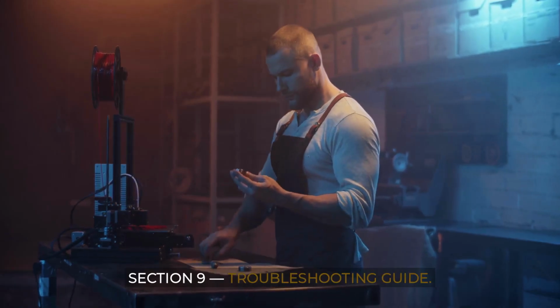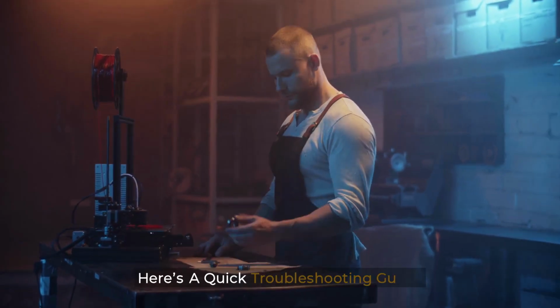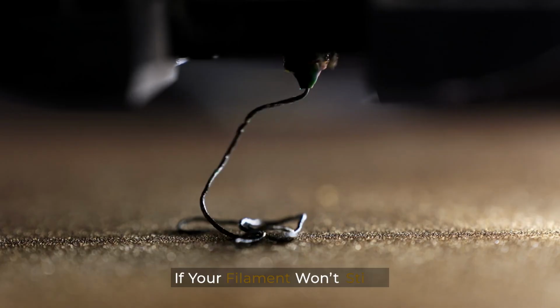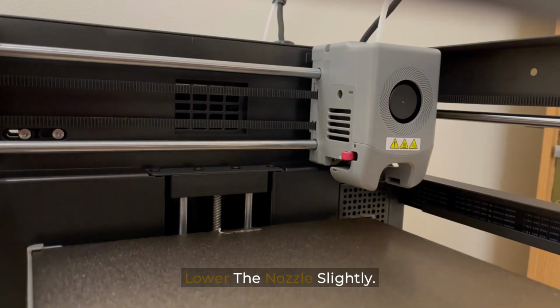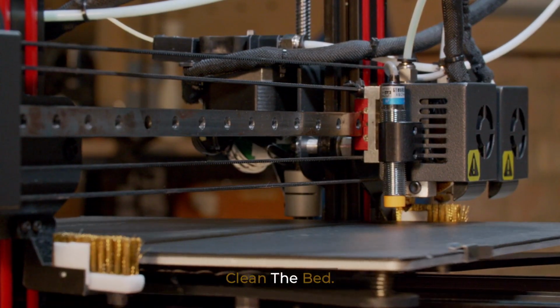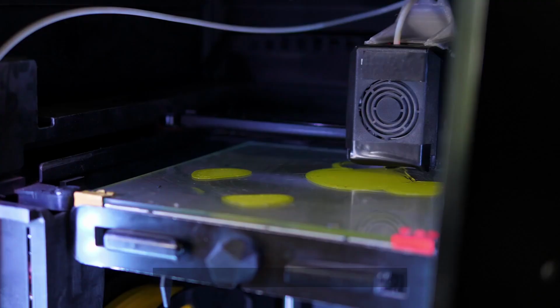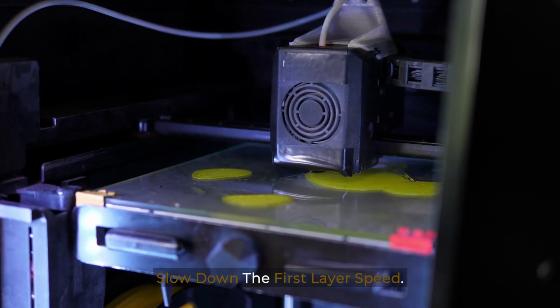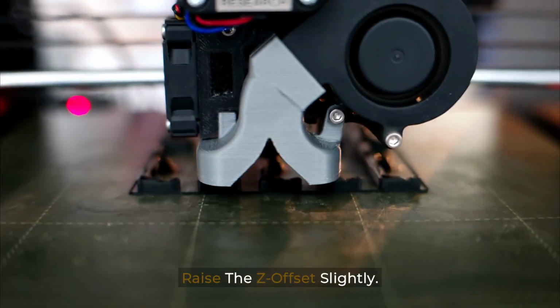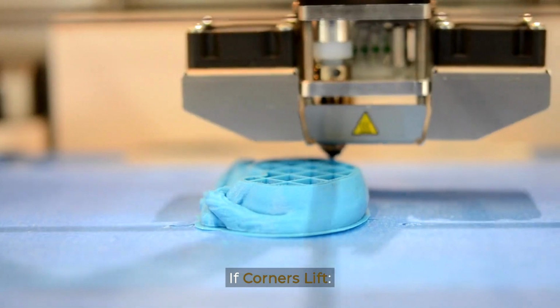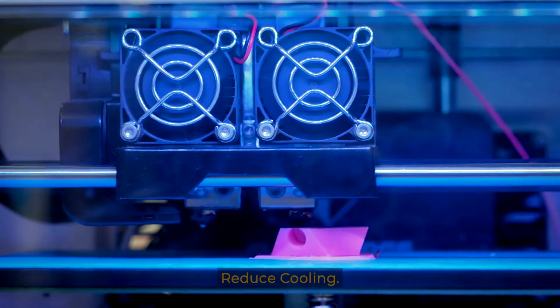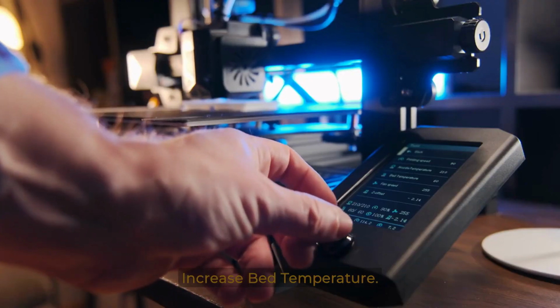Section 9. Troubleshooting Guide. Here's a quick troubleshooting guide. If your filament won't stick, lower the nozzle slightly. Clean the bed. Increase bed temperature. Slow down the first layer speed. If the nozzle scrapes, raise the Z offset slightly. If corners lift, use a brim. Reduce cooling. Increase bed temperature.